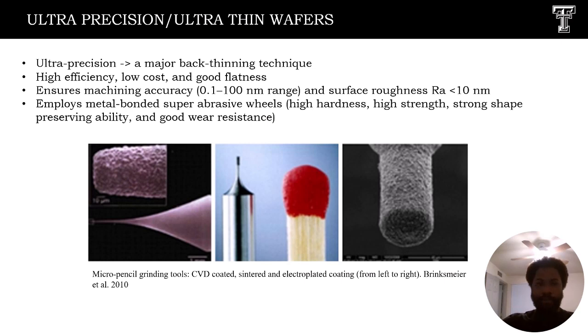Now onto ultra precision and ultra thin wafers. In the semiconductor world, wafer thickness and surface precision are everything. With ultra precision grinding, we can achieve machining accuracy down to 0.1 nanometers and surface roughness below 10 nanometers. That's thinner than a strand of hair, I think. This is made possible using metal bonded super abrasive wheels, which are strong, wear resistant, and can hold their shape during intense grinding.